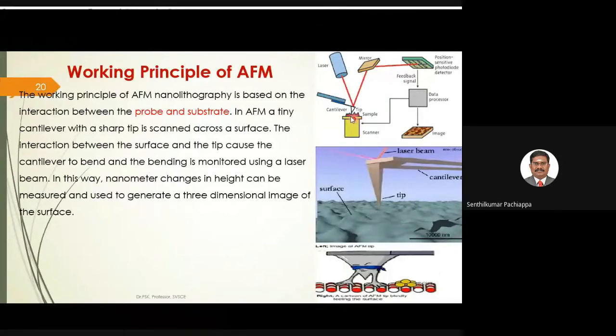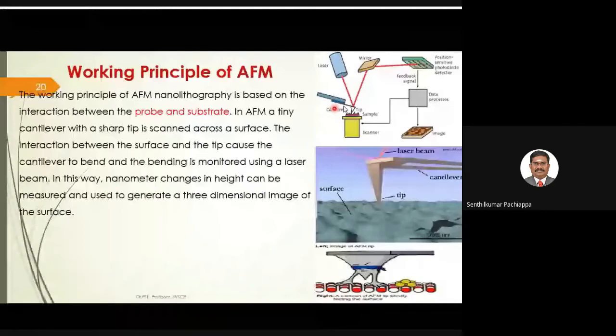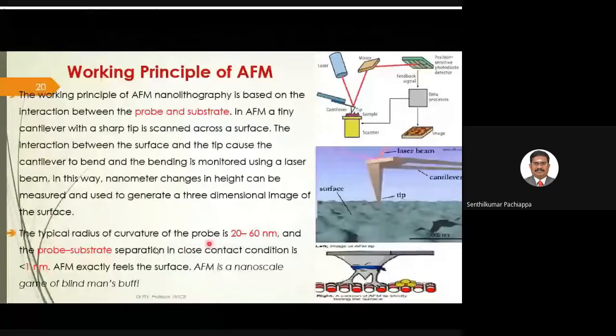This interaction between the surface and the tip causes the cantilever to bend, and the bending is monitored using the laser beam. Here the laser beam is there. This bend in the cantilever is monitored by the laser beam. So this laser beam is used for the patterning. In this way, the nanometer changes in height can be measured and used to generate a three-dimensional image of the surface. The typical radius of curvature of the probe is 20 to 60 nanometer, and the probe substrate separation is close contact condition, less than 1 nanometer.